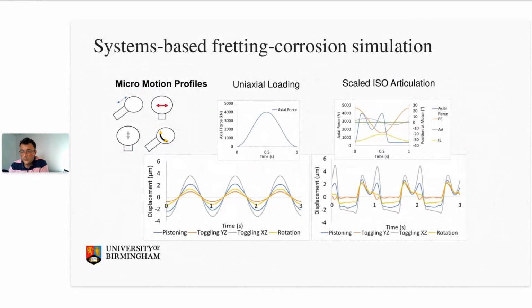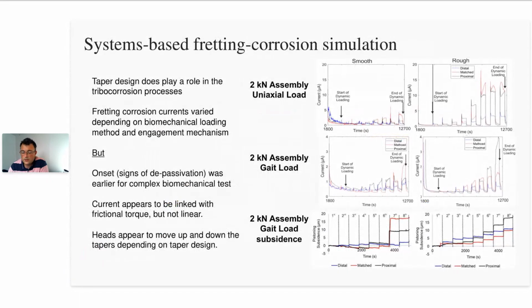So when we look at the fretting corrosion response, unsurprisingly, we can see that the micromotion between the head and the stem is very different under articulation, where we have an axial force and then sliding around that head. We can see that we get more complex toggling and micromotion occurring around that head. But what we also see is that we can link the two of these together and ultimately start to understand a bit more about what's happening at these interfaces.